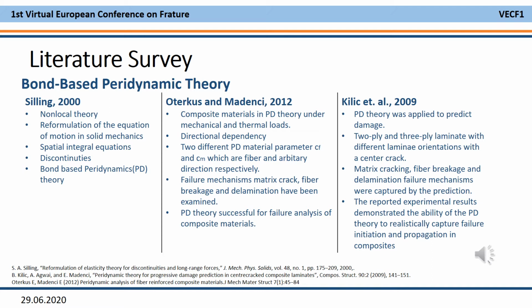Kilic et al. did research on peridynamic theory using 2-ply and 3-ply laminates with different lamina orientations with a center crack. The peridynamic results were validated with experimental data. The failure mechanisms, matrix crack, fiber breakage, and delamination, were captured by the prediction. The reported experimental results showed the ability of peridynamic theory to realistically capture failure initiation and propagation in composites.